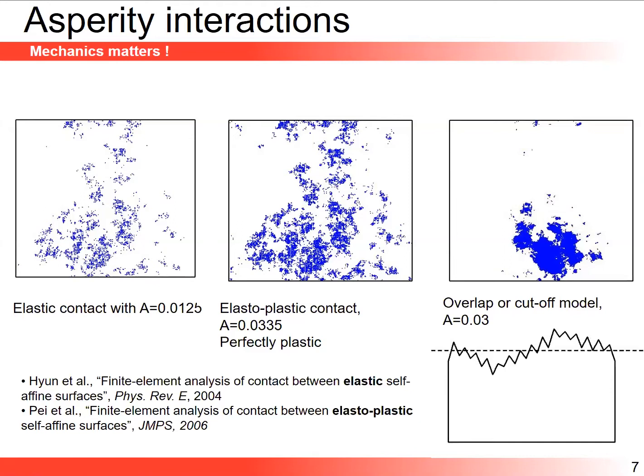And if you apply the scheme to a 2D rough surface, and here the square is looking down at the contact surface, with this overlap model you find this kind of bulky, complex geometry, but more or less bulky blue contact. However, if you account for bulk elasticity interactions, when you press on an asperity, you have long-range elastic forces with slow decay. A point force decays as 1 over the distance to the point source. So it's a slow decay. And you see that if you have elasticity, or here elastoplastic contact, when you push an asperity, you bring down the neighboring asperities and you bring up microcontacts that are further away into contact. So mechanics matters, which is good news for us with a mechanics background.